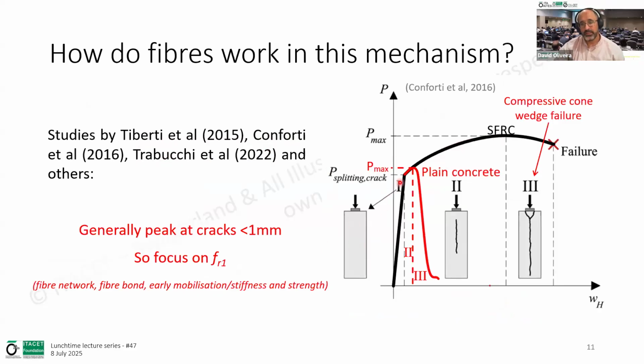And what they observed, having done quite substantial experimental work and tested a number of samples, is that there are generally three phases of fiber reinforced concrete under these highly concentrated loads. We have a first phase where the concrete remains relatively elastic, up to a point where you get the first splitting crack. So if you have an unreinforced concrete, you have your brittle failure. But if you have your fiber reinforced concrete, and you see here in particular steel fiber reinforced concrete, you have a hardening process because the crack starts to develop, and because of the increasing length, you start to gain some resistance from that splitting crack up to a peak value, where beyond that, stage 2, you develop this compressive cone wedge failure, and then you get your total failure.